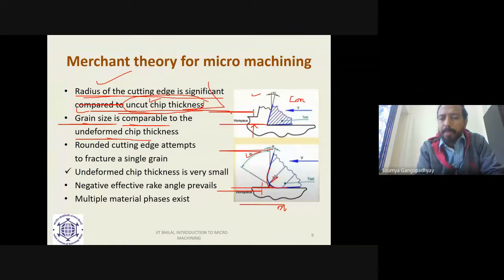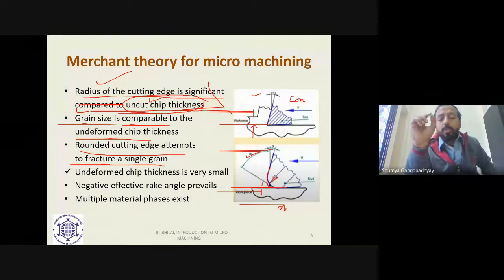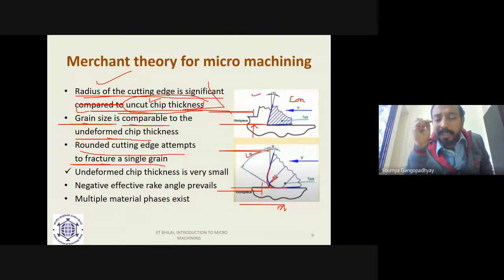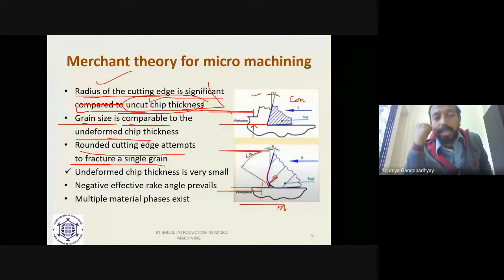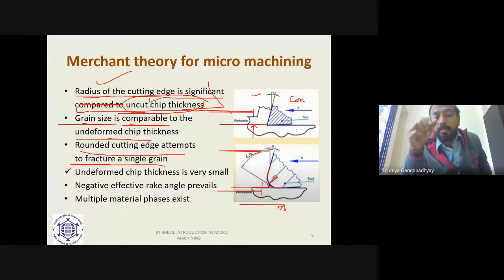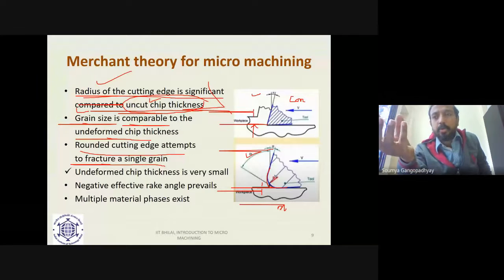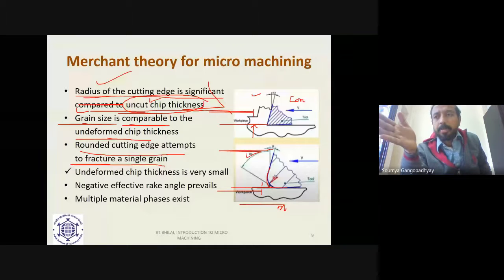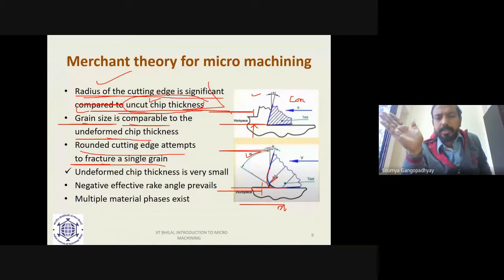And that makes the things complex, because this rounded cutting edge actually attempts to fracture a single grain. And that's why when you are trying to attack a particular single grain, it will experience more resistance. The grain will offer more resistance compared to the grain boundaries. Grain boundaries, as you know, are weaker, and the deformation takes place through the grain boundaries, and it is easier because that is the weakest path. But when you are encountering a single grain, then it becomes difficult to cause fracture or deformation.